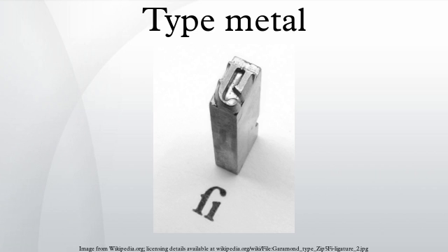Ternary mixtures: adding tin to this bipolar system complicates the behavior even further. Some tin enters into the eutectic. A mixture of 4% tin, 12% antimony, and 84% lead solidifies at 240 degrees Celsius. Depending on the metals in excess compared with the eutectic, crystals are formed, depleting the liquid, until the eutectic 4/12 mixture is formed once more. The 12/20 alloy contains many mixed crystals of tin and antimony. These crystals constitute the hardness of the alloy and the resistance against wear.